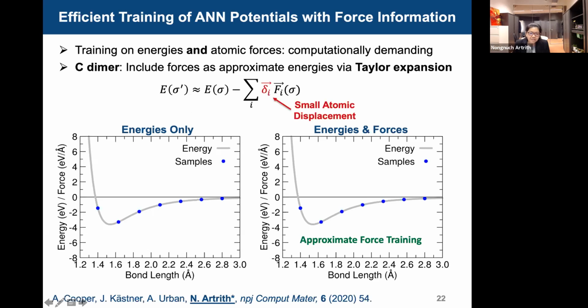On the left-hand side, energy fitting only. The gray curve is the potential energy surface that we would like to describe for the carbon dimer. And the example of DFT data points, just in blue, we have only 7 data points. Then we use these 7 data points and train neural potentials. You can see that it almost predicts right, but it's still wrong in structures and also wrong in the energies.